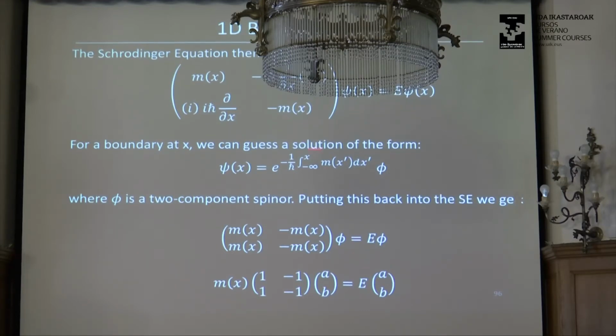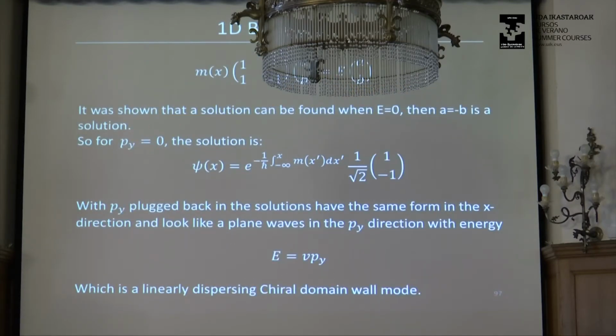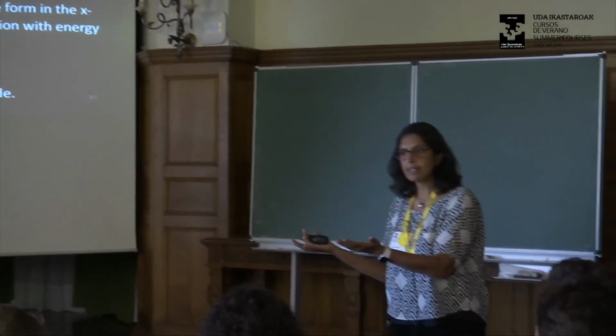And then you can take this ansatz and put it back into the Schrodinger equation. And then you get a very simple matrix that looks like this. And it can be shown that you can find a solution for this when the energy is 0, right? So for this 0 energy, this is your solution. Now remember, we set py to 0. If you put py back, py just gives you plane waves going along the y direction. So basically what this looks like is a bound state in the x direction with a linearly dispersing mode going in the y direction. Okay, so this is just for a topological insulator where you have a plus mass on one side and a minus mass on the other side.